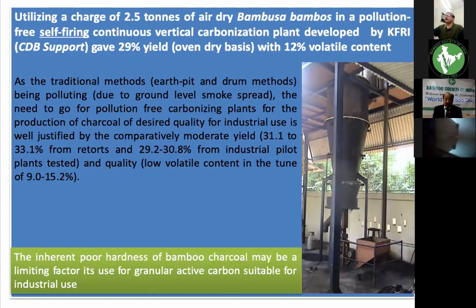The issue is that the inherent poor hardness of bamboo charcoal may be a limiting factor for its use for granular active carbon suitable for industrial use. This type of carbonizer was produced in a project using coconut shells for producing charcoal of good grade suitable for production of activated carbon, granular carbon, without pollution. What we found when we employed bamboo charcoal is that the hardness of the product, an inherent quality, was not as good as compared to other charcoal origins like wood or coconut shells. So this is a limiting factor for its use in granular active carbon, where hardness is very important. That is the only limiting factor.